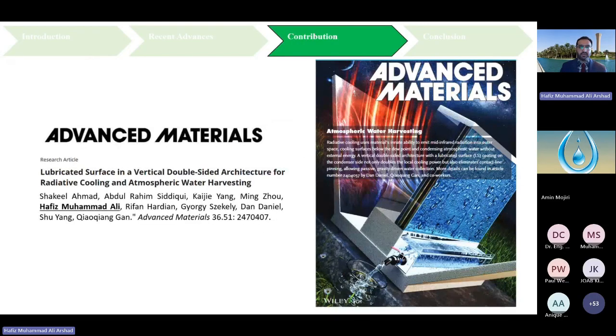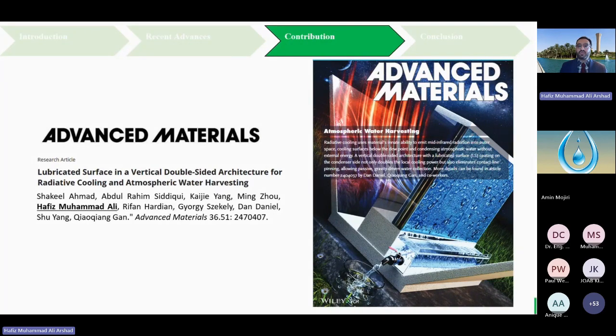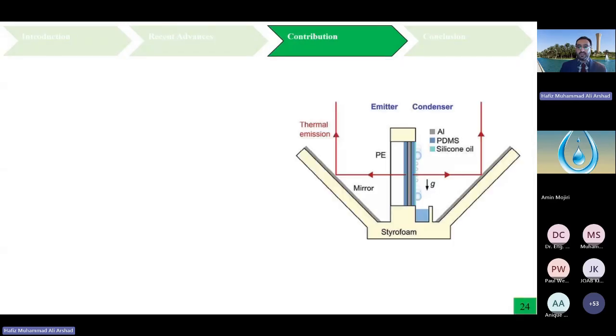Some of the work that we have done with our team on atmospheric air water harvesting, I would like to present here. We used a double coated emitter. In this case, one side was covered with polyethylene so that we have no convection on that side, so the impact of radiative cooling can be seen. This is a mirror, which is an aluminum mirror.